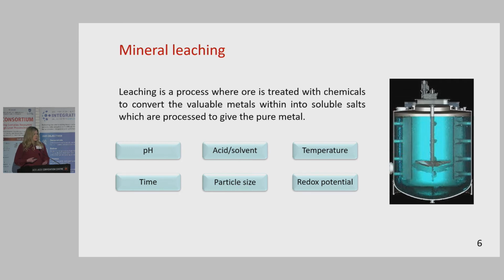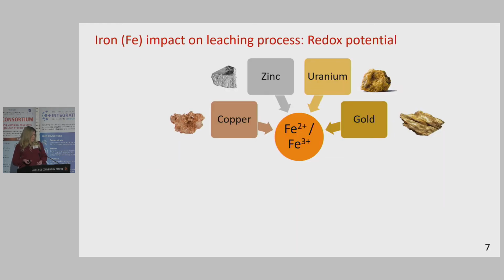Now let's return to mineral leaching. It's a process where we dissolve the ore in acid or solvent to recover the valuable mineral. And it is governed by several different parameters since it's a chemical reaction. For example, pH, time, and temperature, which are fairly easy to measure and control. Others are a bit more tricky, like particle size and particularly the redox potential. So in the leaching process of copper, zinc, uranium, and gold, the redox potential is controlled by the ratio of iron 2 to iron 3 ions in this process.